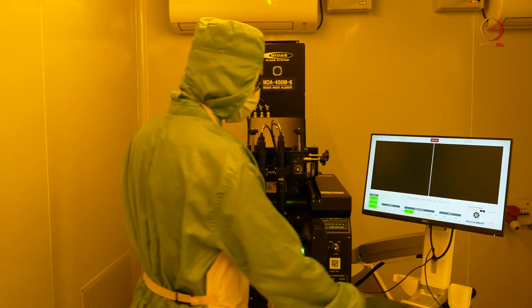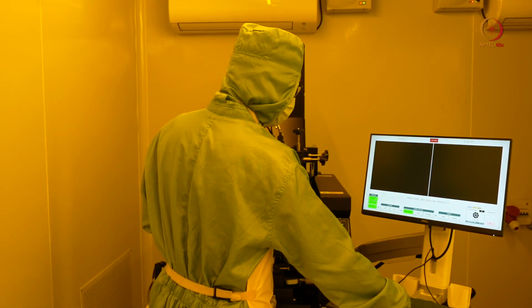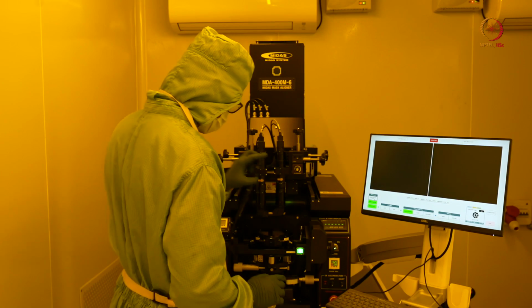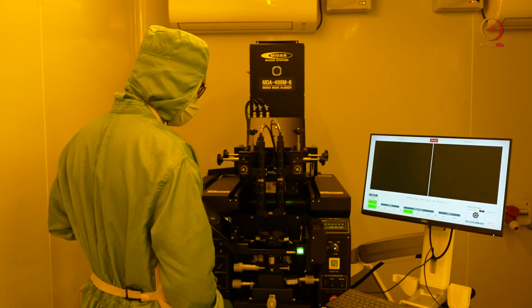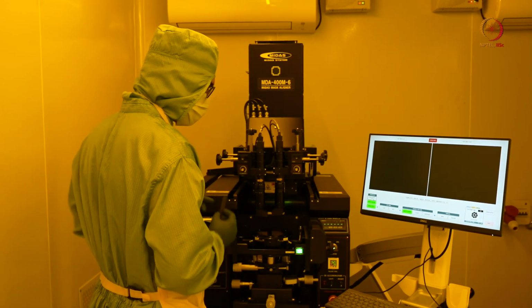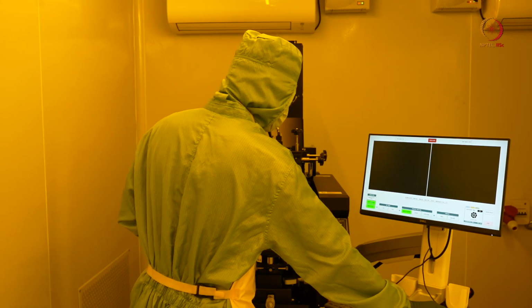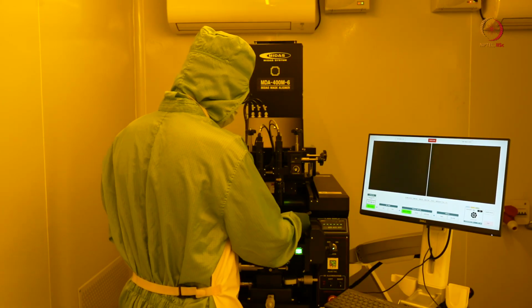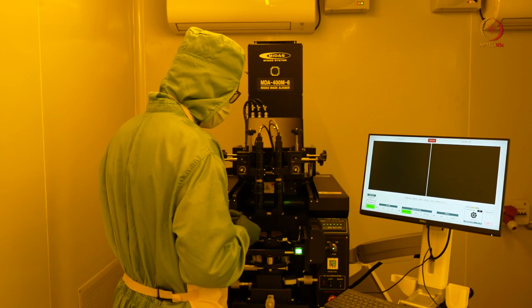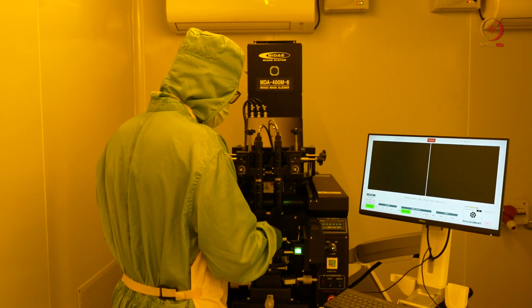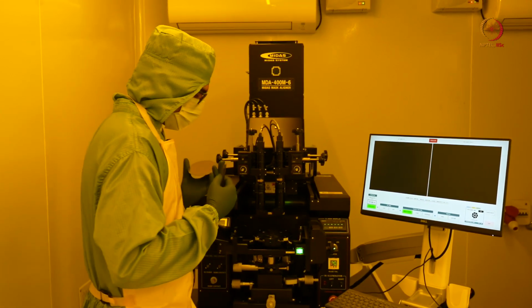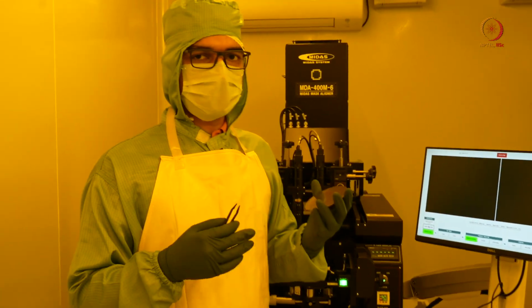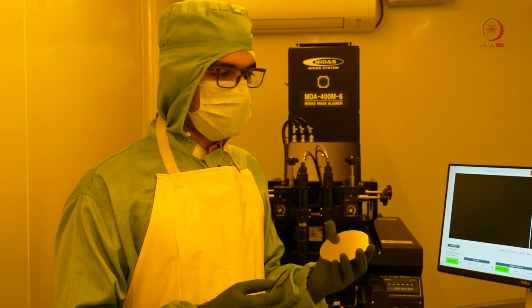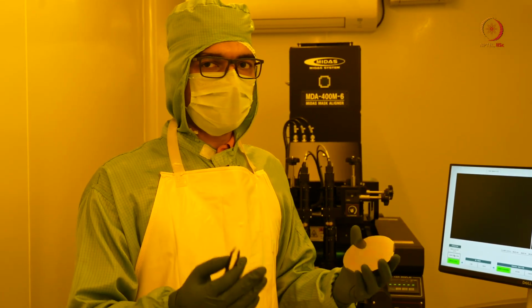So now that the exposure is done, I am removing the mask holder lock so that I can open the mask. And then I am going to remove the sample vacuum so that I can remove the sample from the chuck. So now the exposure is complete, and the next step is to do the post exposure bake, so that we can develop the wafer later.